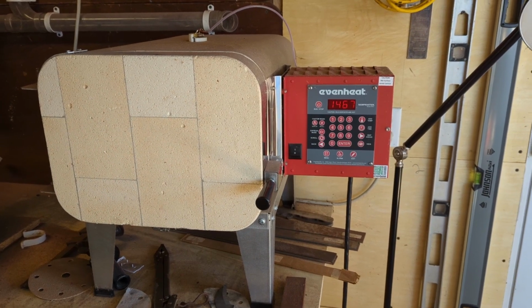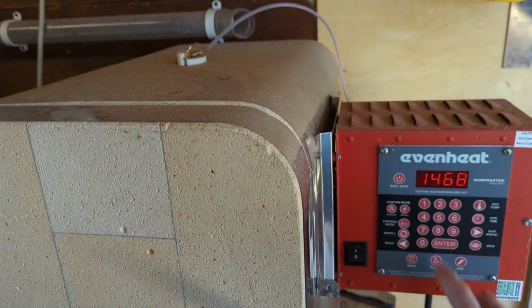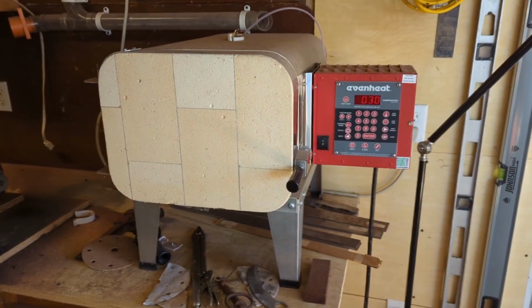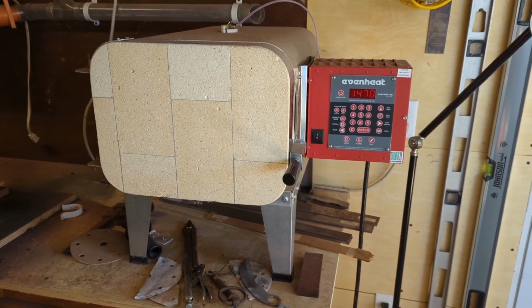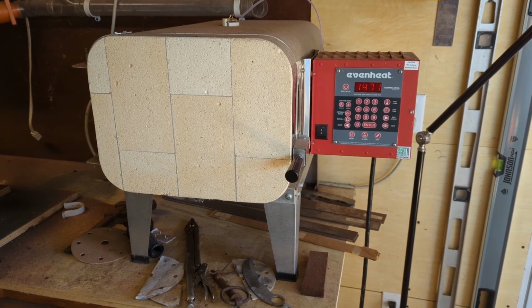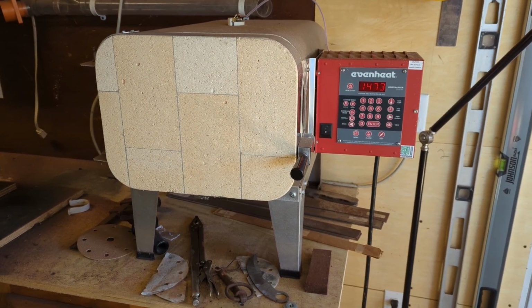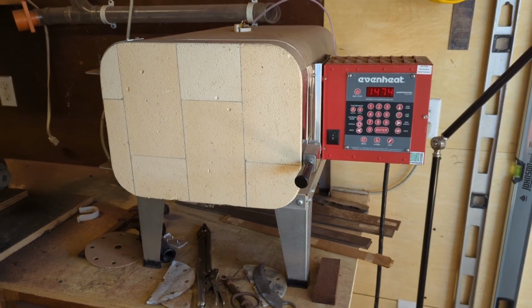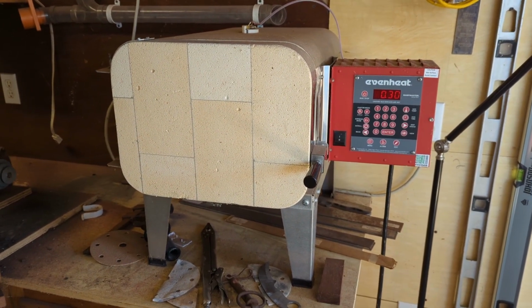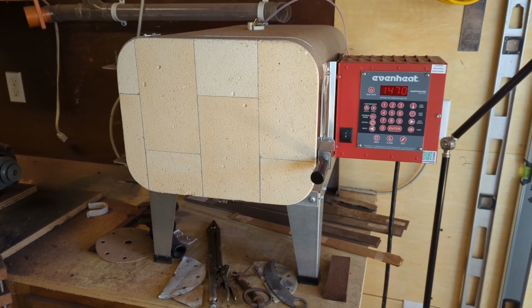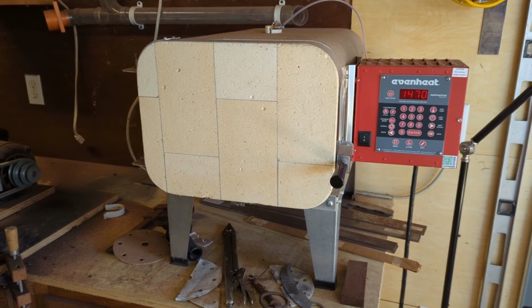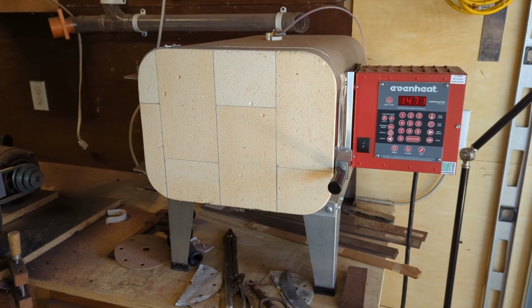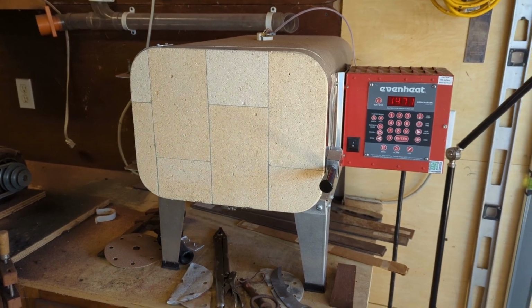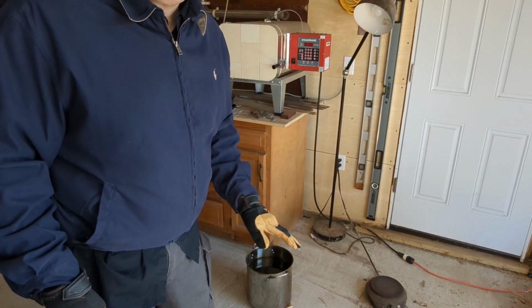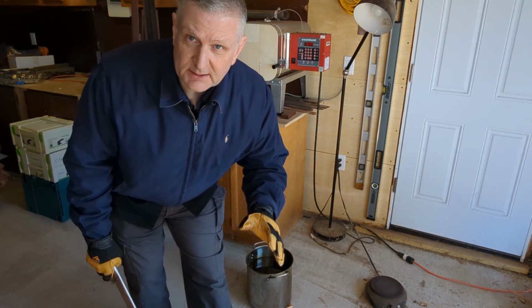And how long you hold it, let me shut this buzzer off. And how long you soak it at that particular temperature depends on the thickness of the piece of steel that you're heat treating. Now, I'll probably, after 20 minutes, pull the smaller knife out. That's 1/8 inch 01 tool steel. Then, after I quench that one, I'll go back and pull the larger blade out, which is 5/32. The 20 minutes hold is actually sufficient for both of them, but that's the order that I want to do this in.